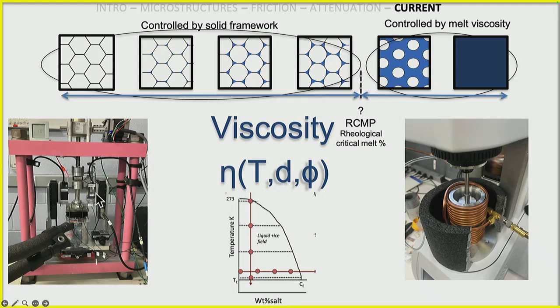Over here, we can do this with that pink apparatus that we were going to use for attenuation, and she has in fact started those experiments. And then to come from this side, we need a different kind. It's a rheometer. So it measures the resistance, the torque needed to spin a little bob in a cup. And so we calibrated it with motor oil and silicone oil and things like that, and it'll get us through slurries on this side.